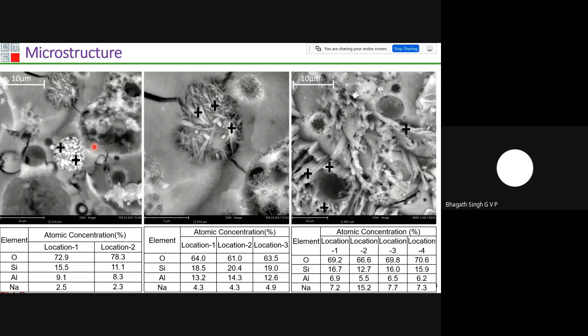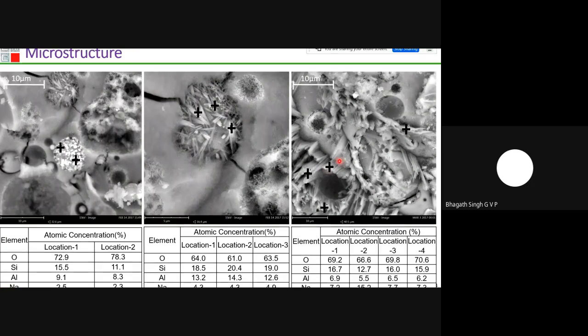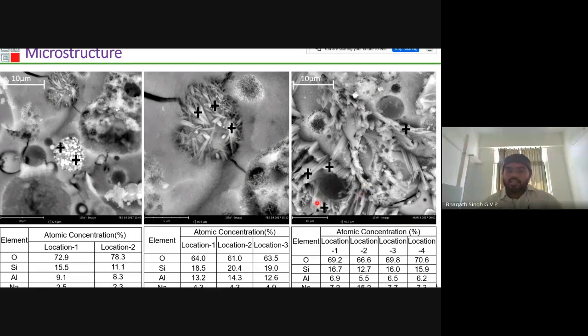I have tried to identify them with this microstructure, and I have observed thermocol-like whitish dot particles over the image, and I have carried out the EDX analysis on these types of particles, and these are all chabazite based particles, sodium based zeolites. And also I have observed small needle types, and also very big needle type new crystalline phases in my various alkali activated mixes. These small phases and these big needle shaped particles are all sodium based zeolites, because if we have excess sodium, it leads to the formation of zeolites in our system, so we have to optimize those mixes as well.